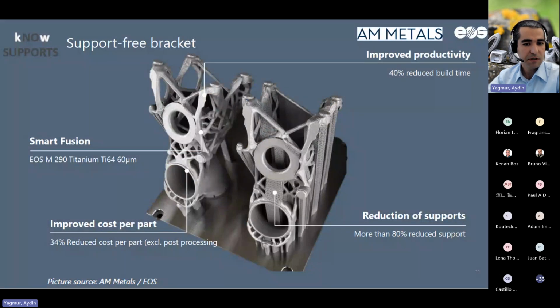This is an automotive bracket from titanium 6-4 alloy that we built with our M290 machine. Smart Fusion is available for all EOS metal machines. This time we used the M290. By reducing the support amount, we decreased the cost per part by 34% because there are fewer supports used, less material used, and build time decreased, so efficiency of the machine increased. Post-processing effort also decreased, with the support amount reduced by 80%.